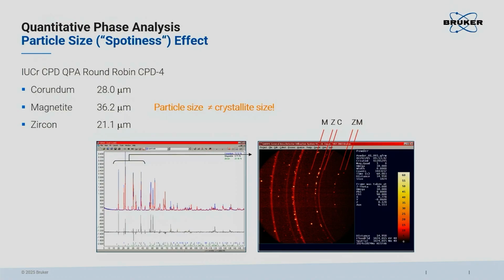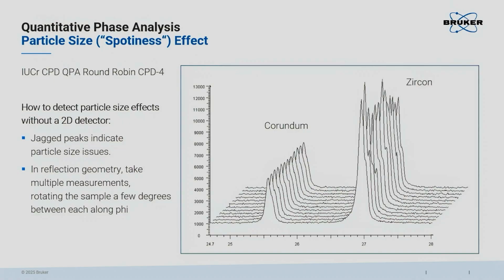But the important point is, if you have spottiness effects, and they are not so easily recognized just from a misfit, then you are done. If you are lucky and you have someone in your lab with a 2D detector, what you would observe is, for example, a pattern like here, that you have nice rings and other rings which are actually more spots than rings. In this moment, if you see such a 2D image of your sample, reconsider, restart, go back to zero. Now, there is still some hope for you who operate standard powder diffractometers with point or with linear detectors.